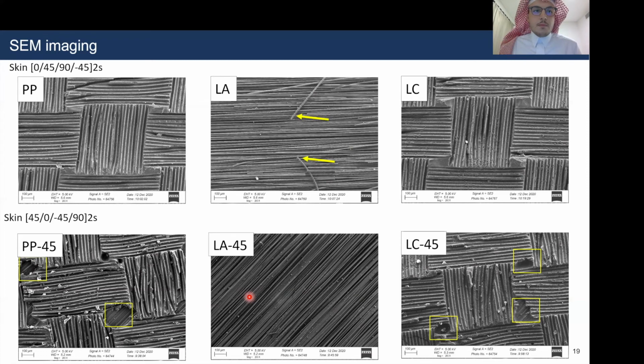Moving on. So after the T-joints experienced the mechanical tests, I will demonstrate now the results that were achieved. We can notice that the first graph here is illustrating the peel ply pre-treated results. We can see that there is a sudden brittle failure at the peel ply pre-treatment. And this happened at very low loads and very low extensions.